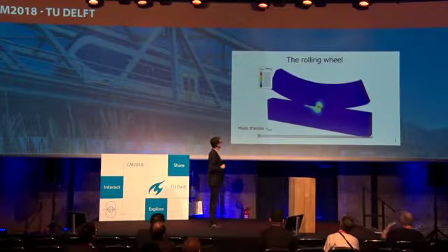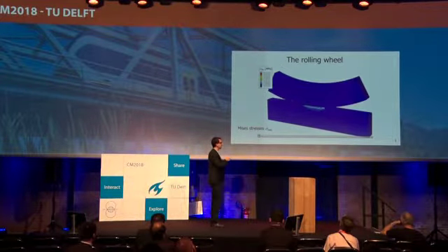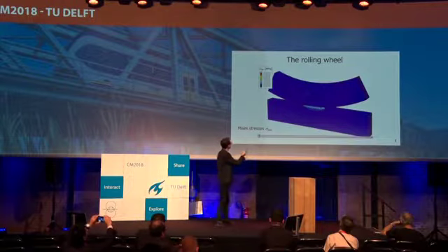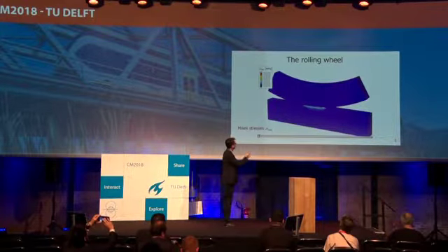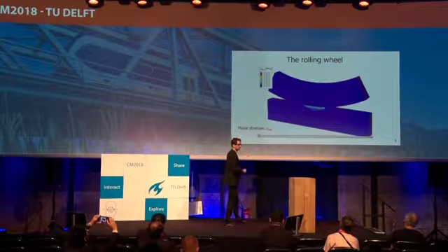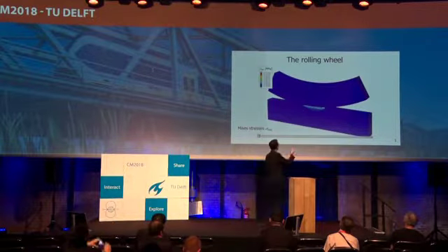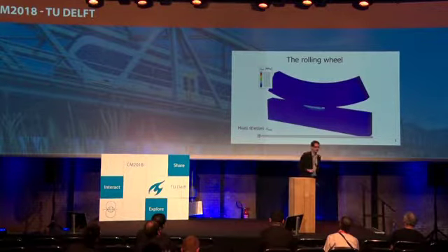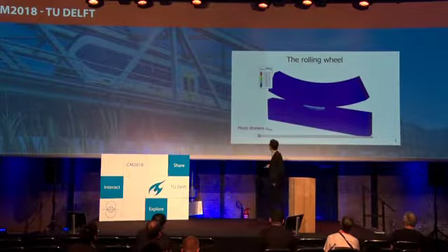Now it's working, great. Here you see, that's the 3D model. We press the wheel onto the rail, we roll over a certain distance, and here we see there was some plastic material behavior in there. We see some remaining von Mises stresses, residual stresses due to that rolling.